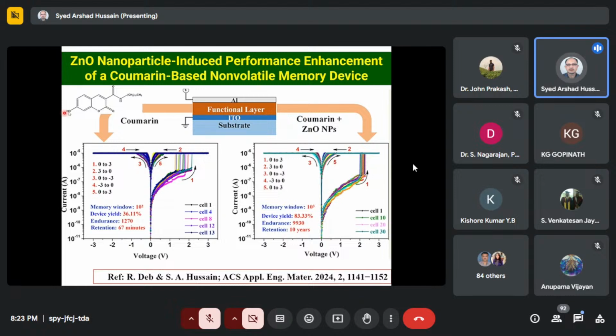Then we have demonstrated nanoparticle-induced performance enhancement of a coumarin-based system. Here we have seen that, for this write once read many kind of memory application, the memory window initially was 10 to the power 2, but when we incorporated ZnO nanoparticles, it becomes 10 to the power 3. Device yield increases from 36% to 83%. Read endurance, initially it was possible to read the stored information around 1270 times, but in the presence of ZnO, it's possible to read around 10,000 times.